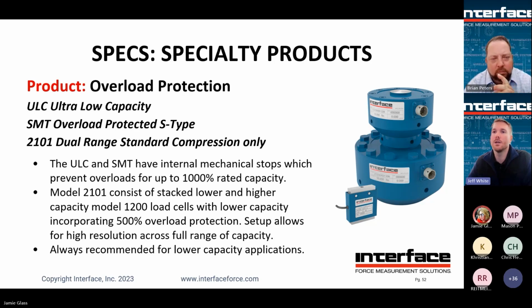The 2101 is the dual range, which allows for accurate measurements throughout the test range. It has 4 to 5 times overload protection on lower capacity load cells, and high output for both ranges, up to 4 millivolts per volt. They are both eccentric load and moment compensated. The SMT we mentioned before can be used in tension and compression. It is micro-sized, has excellent temperature compensation, and is overload protected as well.